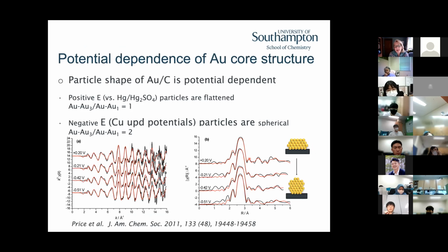One of the beauties of X-ray absorption spectroscopy is you can look from both directions. And in the case of looking from the gold, we see something that's really interesting. If we're not depositing the copper onto the gold, what we can see is that the particle shape of the gold particle sitting on the carbon is potential dependent. So we see variations in the EXAFS spectra as we go from one potential to the other, and you can clearly see things are happening. We take the Fourier transform. Hopefully you can see that there is a bit of difference in the shape of this Fourier transform, especially when you start looking out to the higher shells.